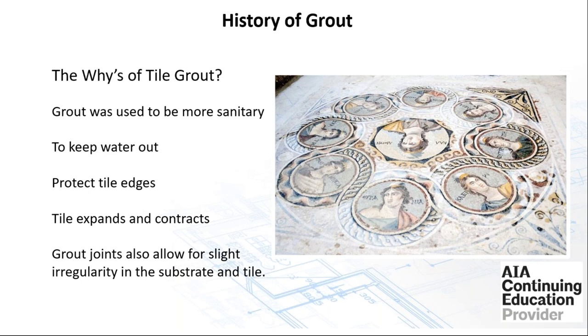true up the tile, to change any imperfections or create any. It's there to fill the joints. I get a question on a regular basis, which grout do you have that is waterproof? Well, it's a simple answer. We do not have a waterproof grout. Yes, we have several selections, different grouts that are more dense, less absorbent, or more resistant to water or moisture. However, grout is not waterproof. It's there to fill the joints and keep out water, again, protect the tile edges. However, it is not a waterproofer, and it does not true up the substrate or take the irregularities in the tile.